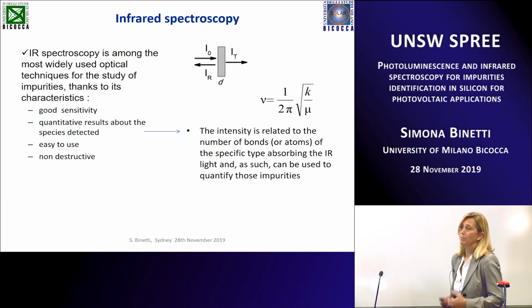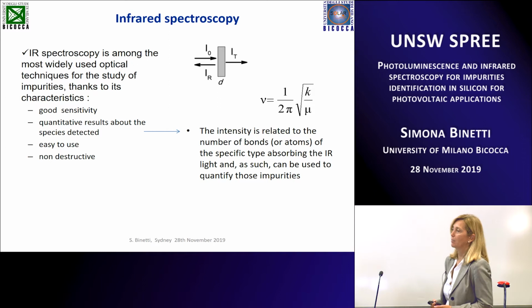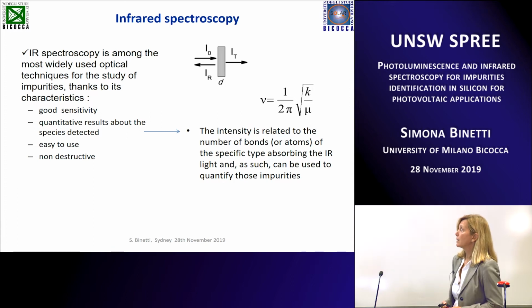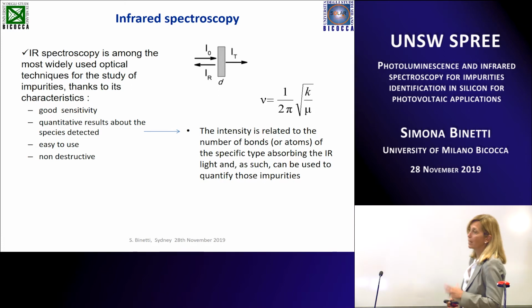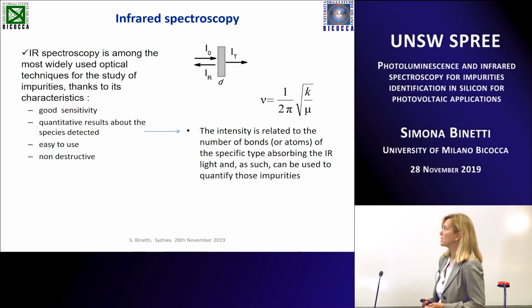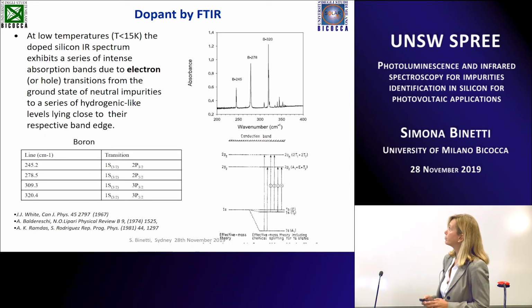Infrared spectroscopy is much more simple. It's very well-known technique. It's used to quantify the impurities in many materials, and in silicon mainly for oxygen and carbon, because it's a good sensitivity, it's very simple, it's non-destructive, and also the most important advantage is that the quantitative result can be obtained because the intensity is related to the number of bonds to the specific type absorbing infrared radiation, and so can be used to quantify the impurities.